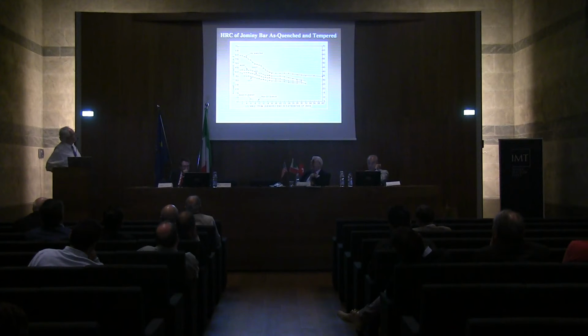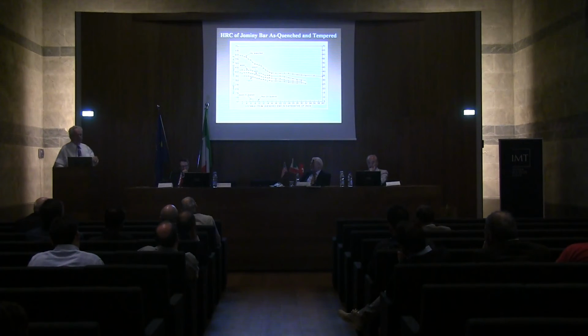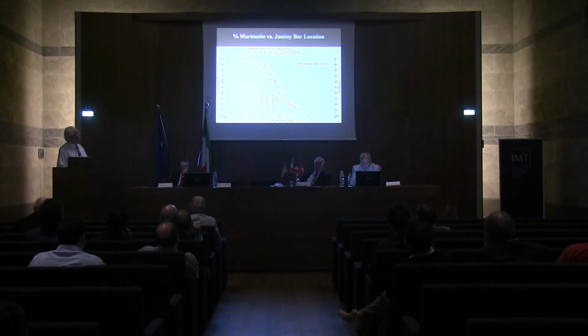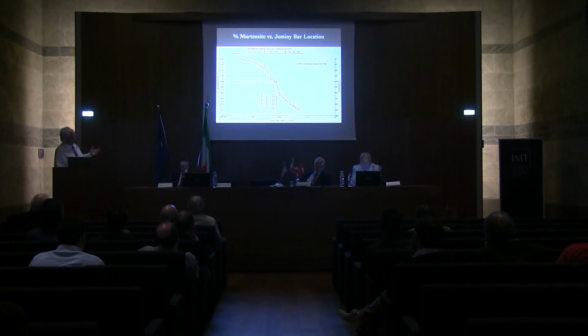And there's Jominy data, hardness in Rockwell C, as quenched, and then tempered at 900, 1,000, and 1,100 Fahrenheit. Because I made Jominy bars, ran them, and then I also tempered them and ran the hardness. And this is percent martensite versus Jominy bar location. And you can see that at a distance of 0.35, on that first one there, we've got about 85% martensite. And it keeps dropping down because we're in the inflection zone. If you're up near the beginning, the water quenched end, it's all martensite.